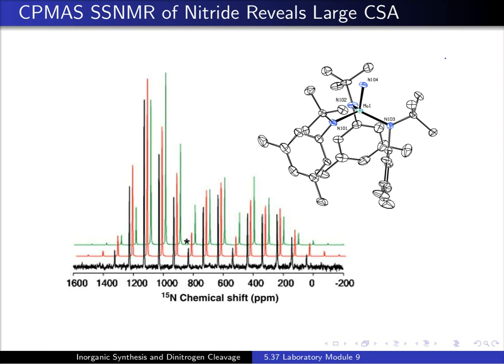Another way that we've been able to characterize these complexes has been through NMR spectroscopy. When we get to the final molybdenum nitride complex, the crystal structure of which is shown here, we have a very short molybdenum nitrogen triple bond. This is about 1.66 angstroms in length. And furthermore, we could derive this species from N15 labeled dinitrogen. And so we can do N15 NMR spectroscopy on this system.